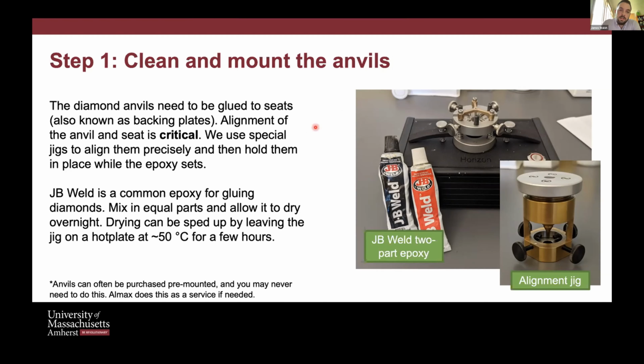So if you're inheriting a diamond anvil cell, or you're buying a new diamond anvil cell, you might not ever have to actually glue the anvil itself to the seat, but it's an important step for reasons, again, Stas touched on. The gluing of the anvil, the diamond, to the seat. You want that to be done in a very precise way so that that culet, the pointy bit of the diamond, aligns well with the whole cell base. If you don't, you can introduce, you know, tilting, and that can come back and bite you during the experiment. So alignment is critical in this step.